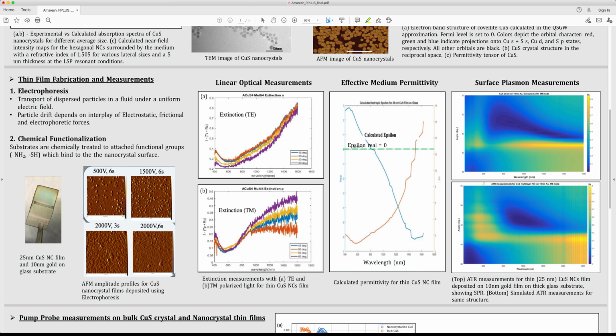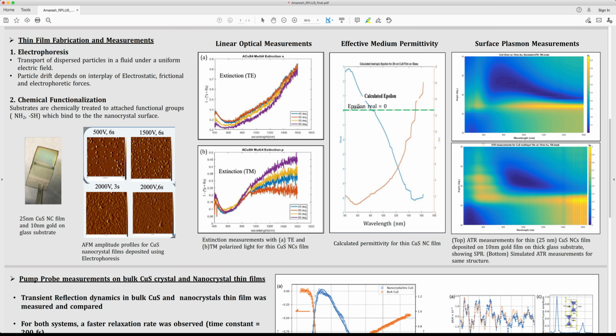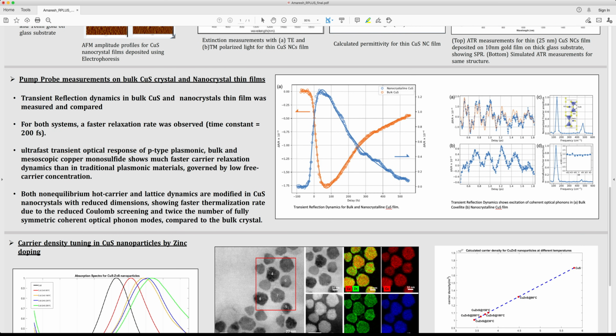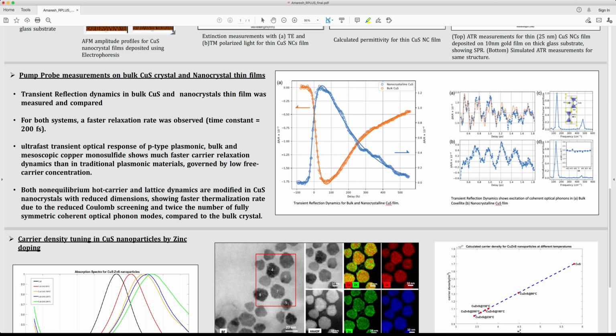We further show interesting physics of thermalization of hot carriers in copper sulfide bulk and nanocrystals using pump and probe transient measurements. The result shows that thermalization happens faster in copper sulfide compared to conventional metals owing to the lower carrier density in copper sulfide. We also detect coherent optical phonons in the bulk CuS crystals as well as in the nanocrystal films.